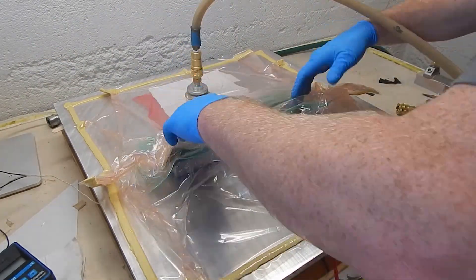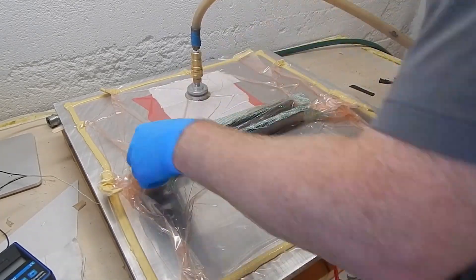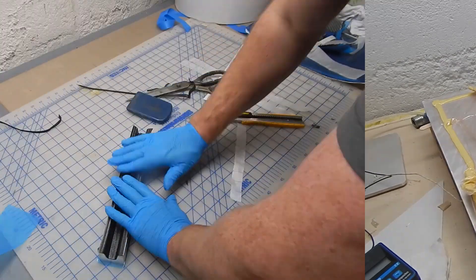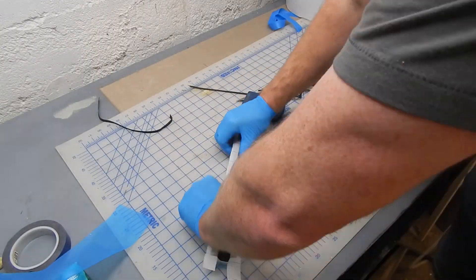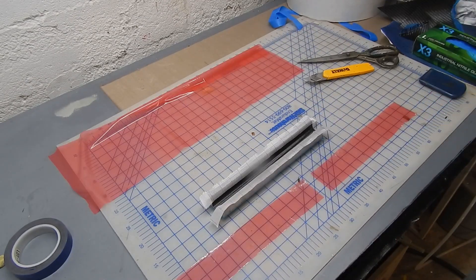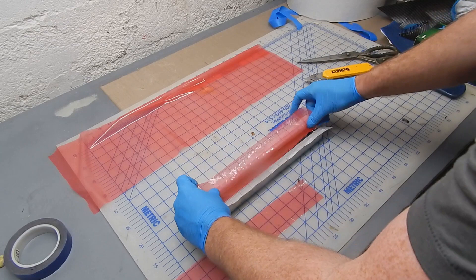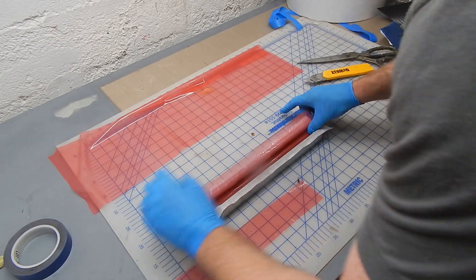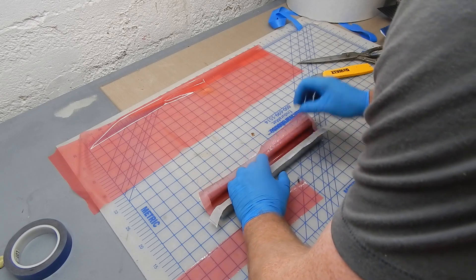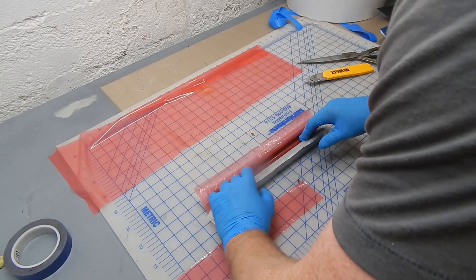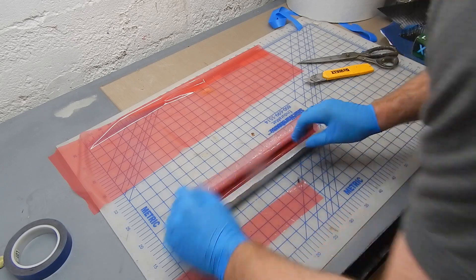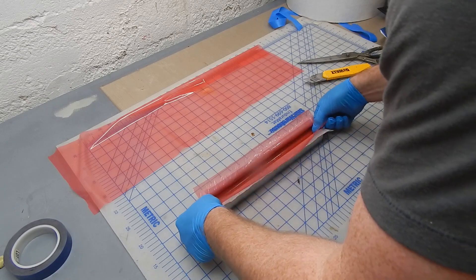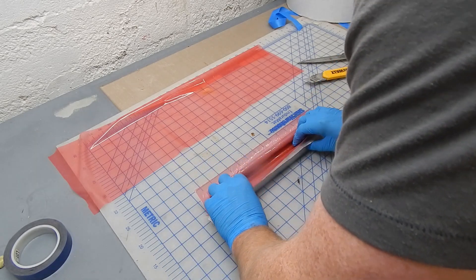And here it goes. Just pull it down, I end up holding it probably five or ten minutes under vacuum there. Here it is with two little strips of peel ply where the surface is going to be bonded onto the panel, and two pieces of non-perforated fluoropolymer release film. And I'm doing it in two pieces so that they don't bridge in the bottom. This is essentially a slip joint, so that even though this is really stretchy, I want the pieces to be able to slide by each other and not have any unnecessary stress that might hold up the laminate to bridge the corners of the part in there.